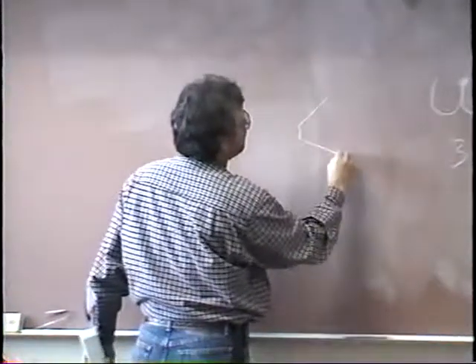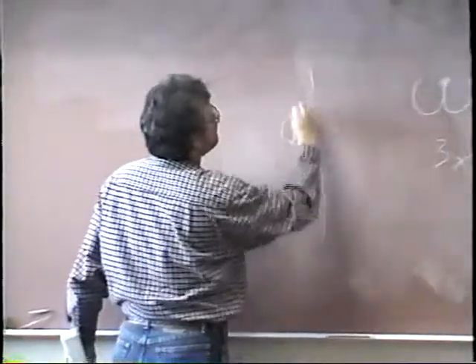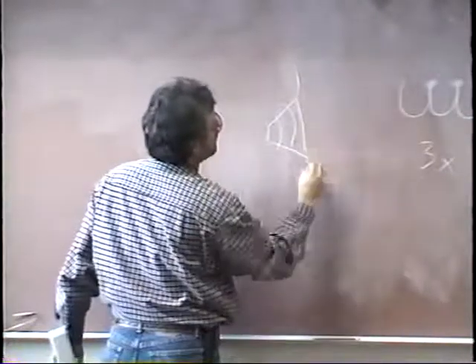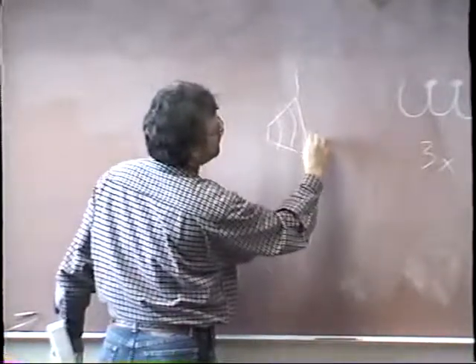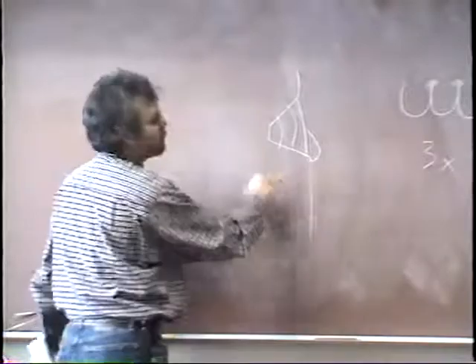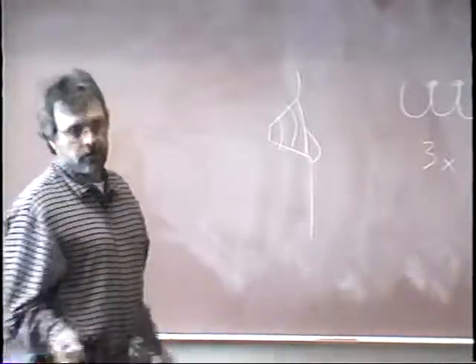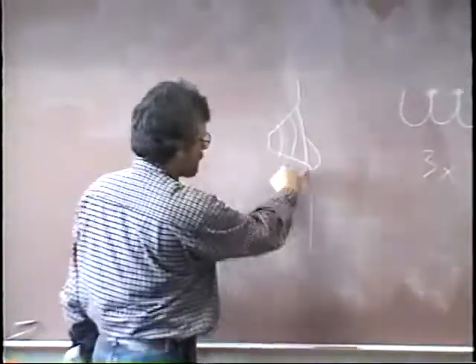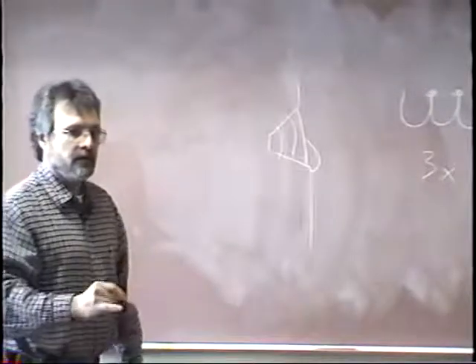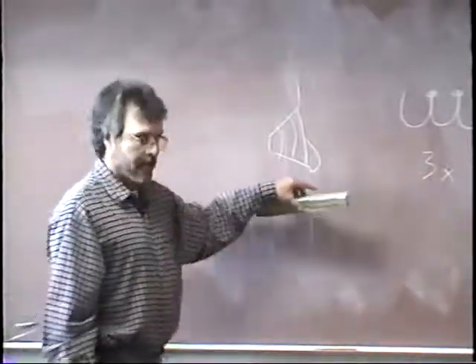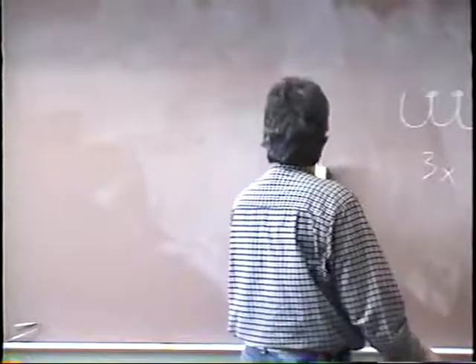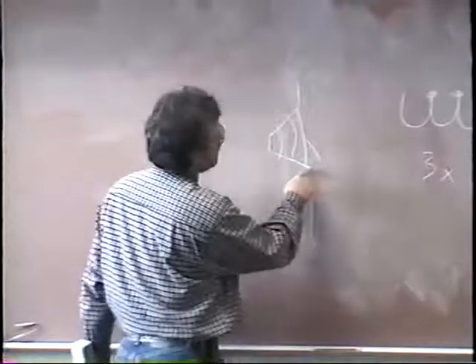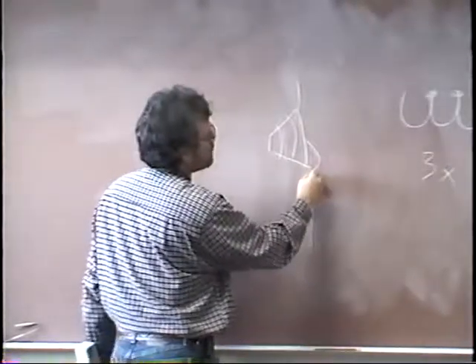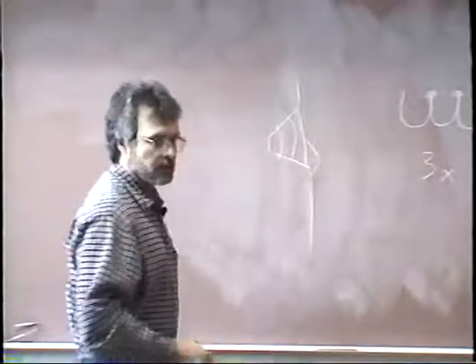What he's saying here is we've got this sucker all filled, and he's saying that when you put that first bead on for your cap, you're going to get overlap here, and you can't avoid it. There's no reason for overlap, and overlap is a defect. And if you're welding a code, this will get called on you. If you make that weld and you leave that little edge right there, there's not a reason in the world it shouldn't just blend in just like so.